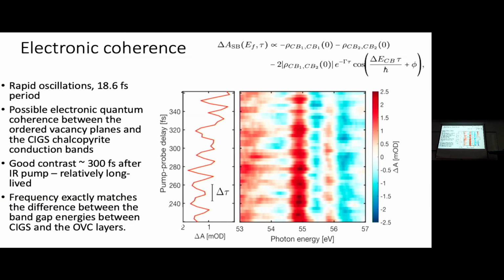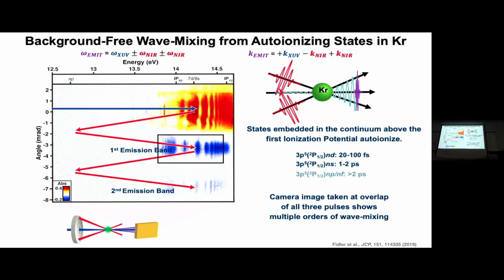It was all very new work, but it looks like a true electronic coherence occurring within each blob of the vibrational phonon coherences. So now all of this was transient absorption, and when you do transient absorption, one pulse excites and then one pulse probes, and you're still doing linear spectroscopy with the probe a little bit. You can't do anything nonlinear, exactly, is maybe the better way to say it.